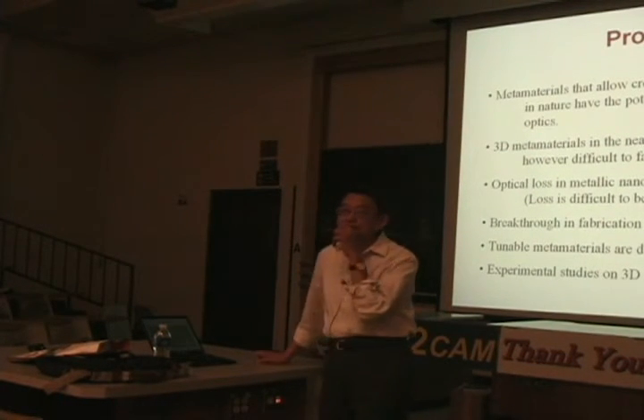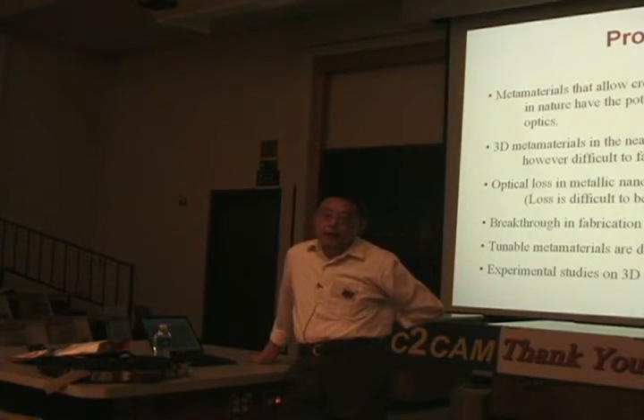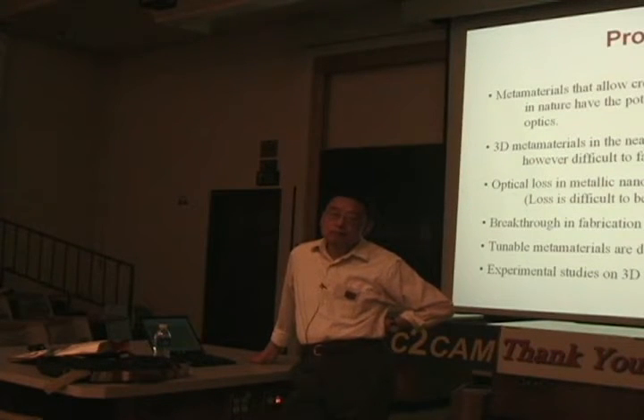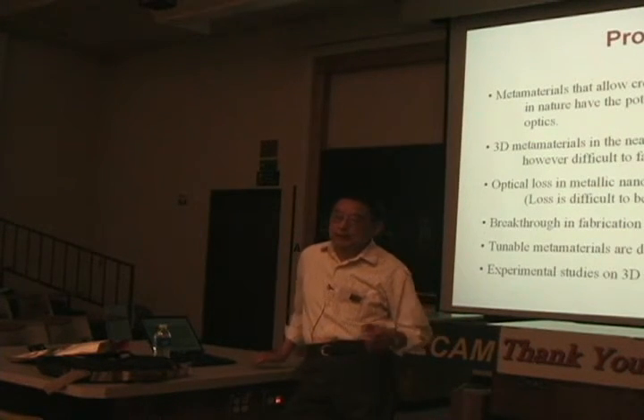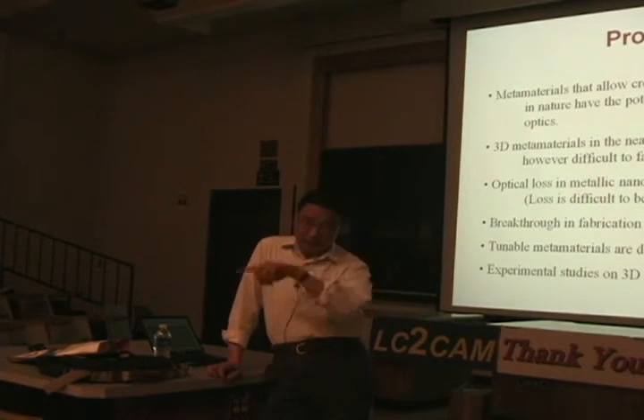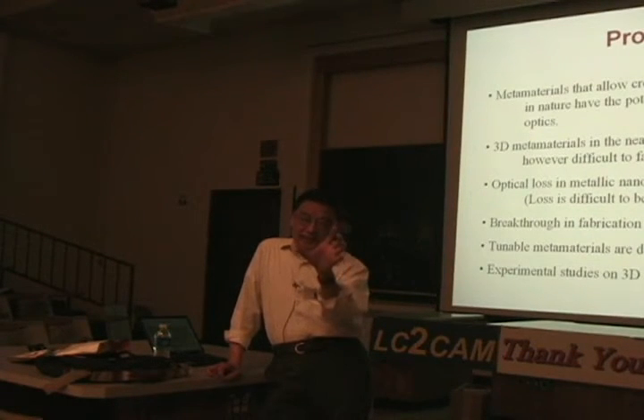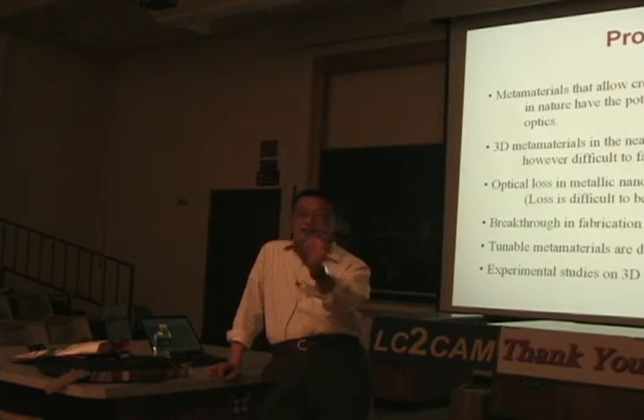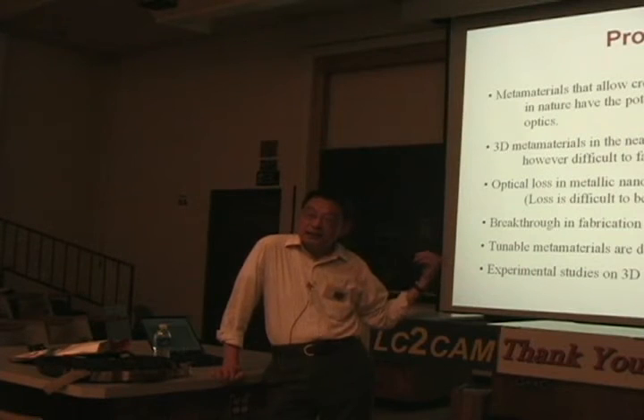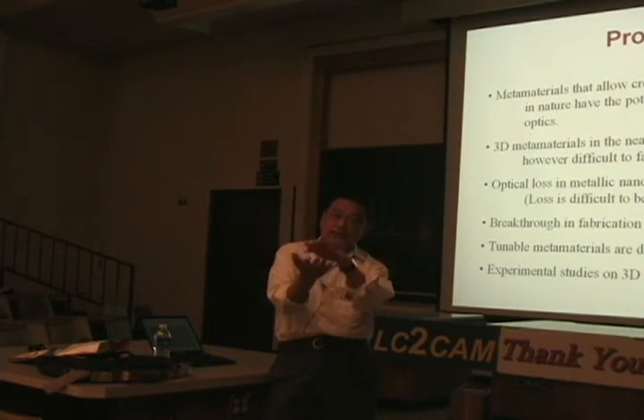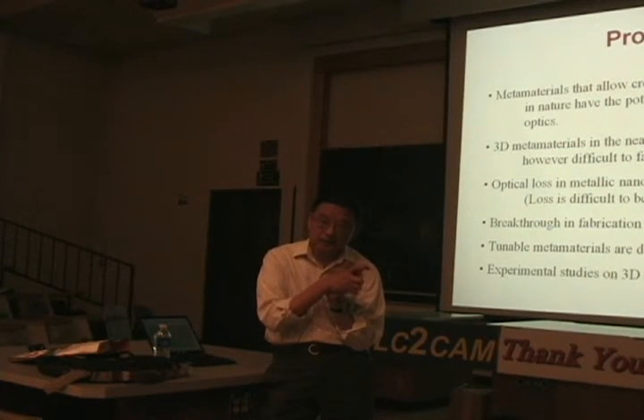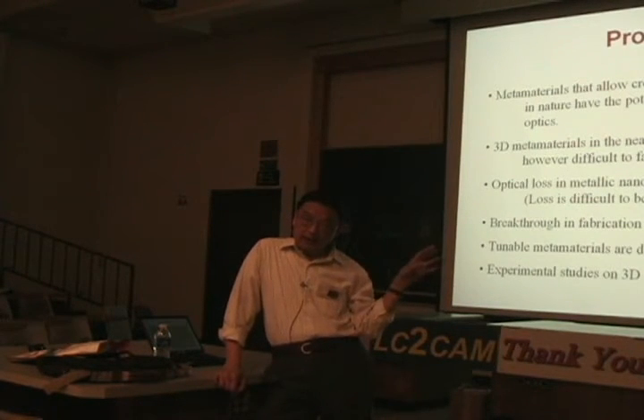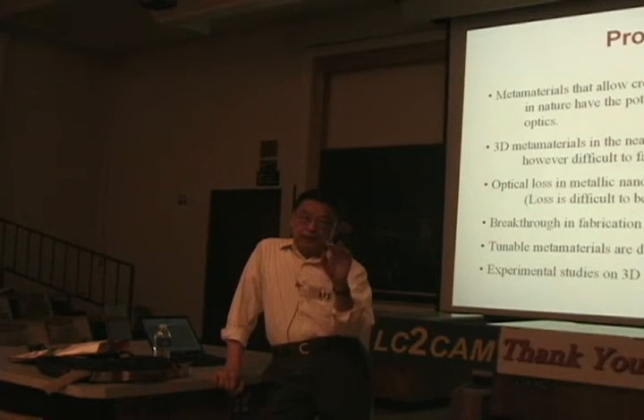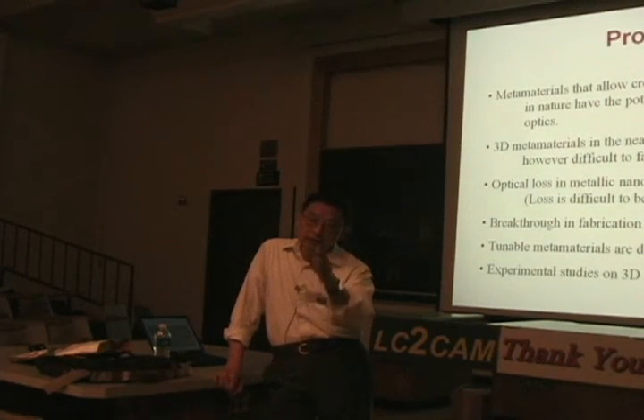We have a question from Ron. So there's a remote question from the Liquid Crystal Institute at Kent. Very interesting talk. We would like to know more about where the nonlinear effect comes from in the fishnet structures, from the metal or the dielectric materials between the top and bottom layers. Well, I just mentioned, we have this nonlinear susceptibility chi. That is mainly from the metal, because actually that particular experiment is done on silicon dioxide. That's the dielectric medium in between, and silicon dioxide is known to have very, very small nonlinearity. So the nonlinearity is mainly, in this case, coming from the metal part. And then through the surface plasmon resonance, we get additional resonance enhancement at the magnetic resonance.